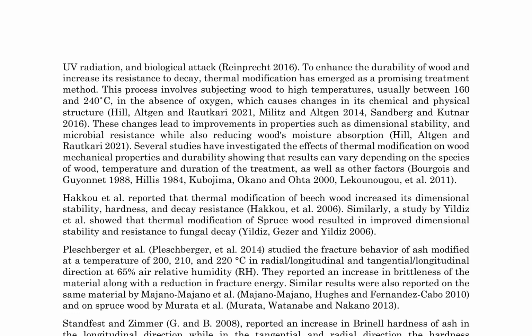Flexure tests on specimens with longitudinal and transverse grains revealed that thermal modification slightly improves the flexural modulus and strength, while reducing statistical variability compared to unmodified samples. However, fracture and Janka hardness tests showed a more pronounced brittleness in the thermally modified samples, with a 47% and 60% reduction in total mode I fracture energy for radial-longitudinal and tangential-longitudinal systems, respectively.